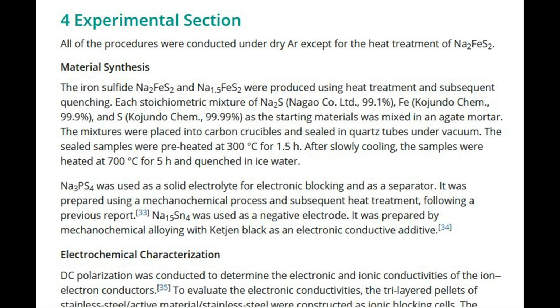Na3PS4 was used as a solid electrolyte for electronic blocking and as a separator. It was prepared using a mechanochemical process and subsequent heat treatment. Following a previous report, Na15Sn4 was used as a negative electrode. It was prepared by mechanochemical alloying with Ketjen black as an electronic conductive additive. Electrochemical characterization. DC polarization was conducted to determine the electronic and ionic conductivities of the mixed ion-electron conductors.